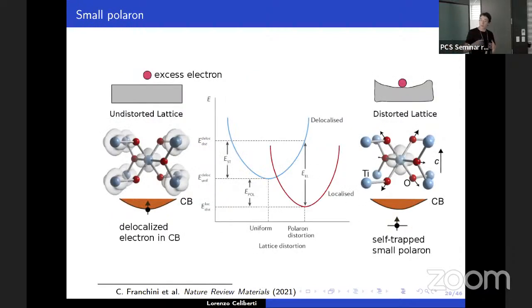And this is what we can see, especially from the DFT calculation. On the left, you take an undistorted lattice with another electron. This electron will fill the conduction band, and you have a delocalized state. But what can happen in these materials is that the lattice is distorted, and you get a localized state in the insulating band. You can define a polaron energy, taking basically the energy difference between these two calculations, which corresponds to the red and blue curve in this case.